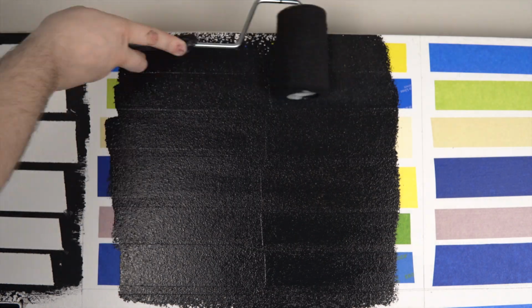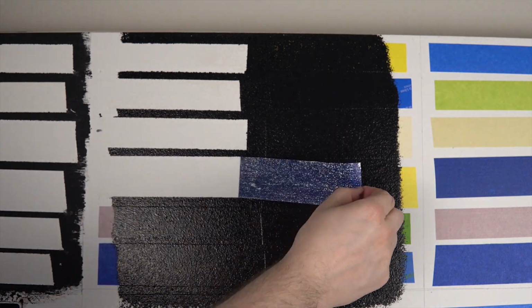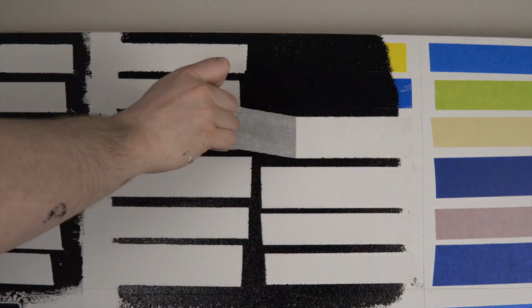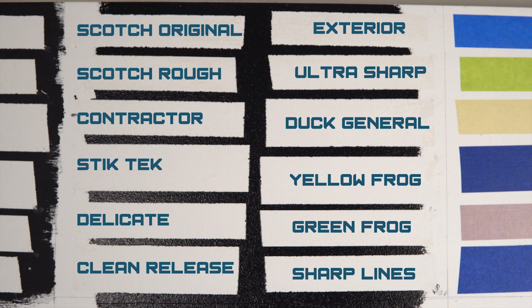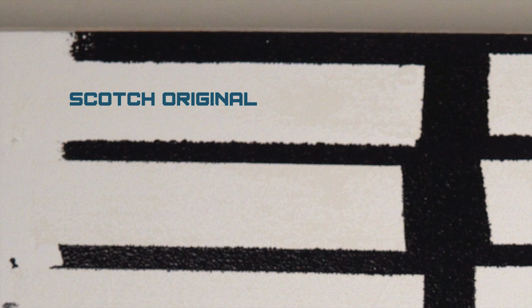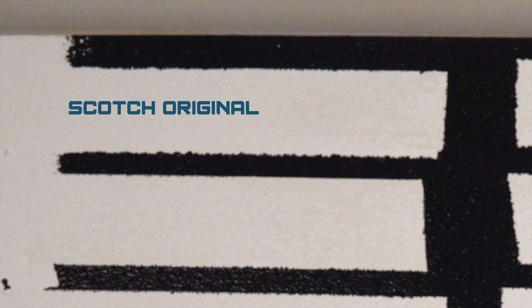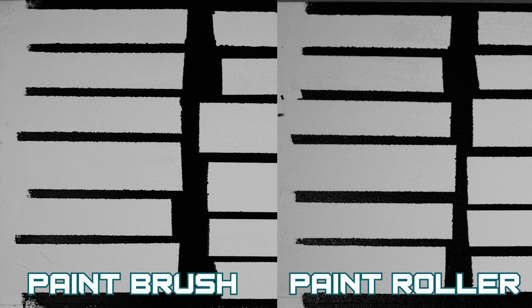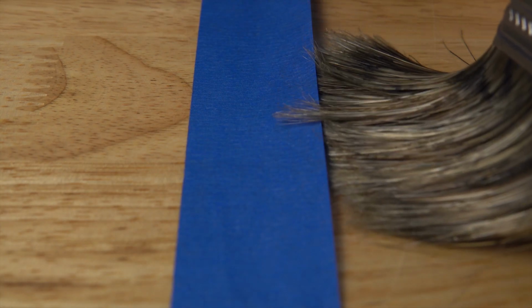Moving on to a roller application with a fine texture, once again, the Frog tapes perform extremely well. Duck Brand Clean Release, Scotch Delicate Surface, and Stik Tek performed very well overall. The Scotch Original and Exterior Surfaces struggled substantially with this test. Comparatively with the brush application, it appears a roller is a lot more forgiving. This can be due to the bristles breaking that edge seal of the tapes and allowing paint intrusions.